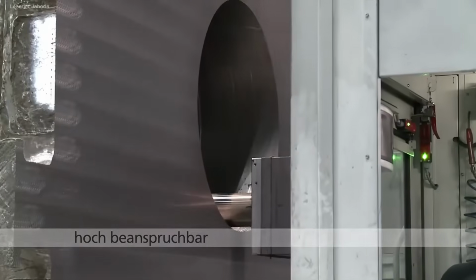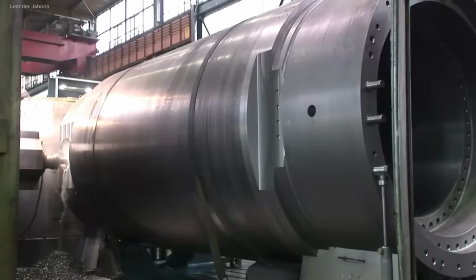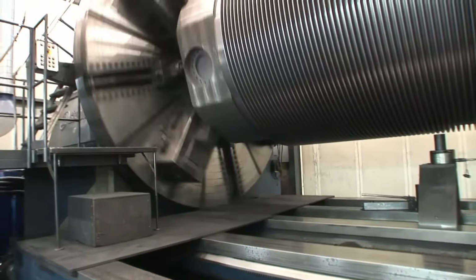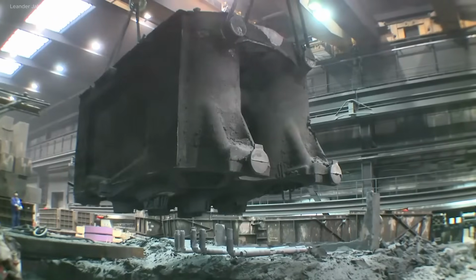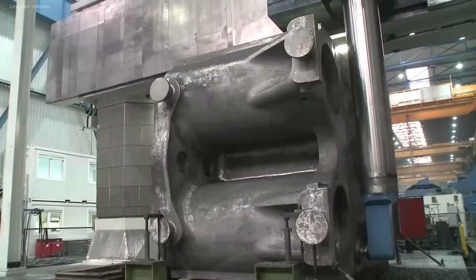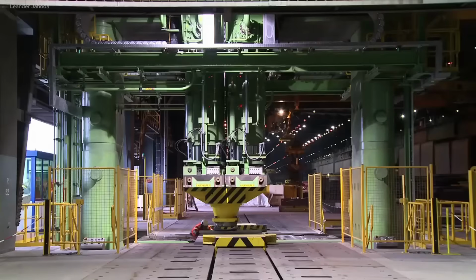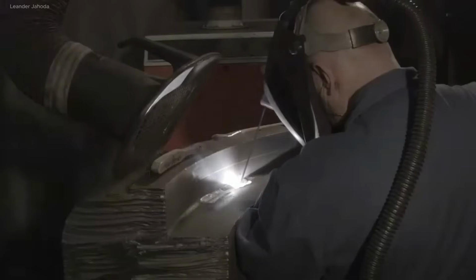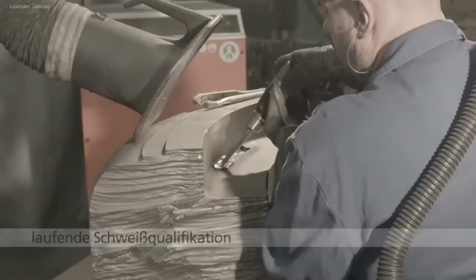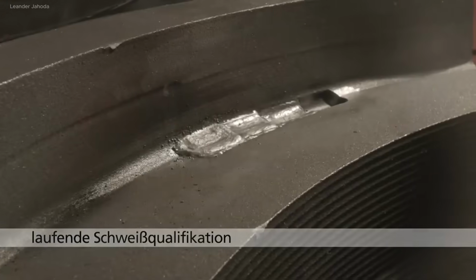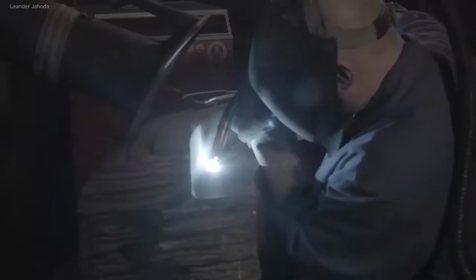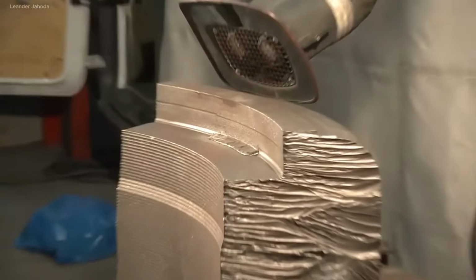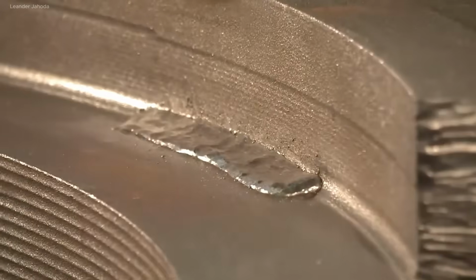This enables deposition rates of up to 0.2 square meters per hour, with layer thicknesses between 0.6 to 0.8 millimeters. The process generates minimal heat input, reducing thermal distortion and eliminating the need for preheating. Robotic guidance ensures consistent weld quality, even on complex geometries or in difficult positions.